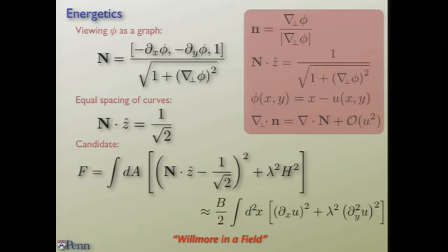The divergence of the layer normal, the normal to that green surface, is to the same order, to quadratic order, the same as the divergence of the nematic director in the smectic. Everyone get it? This lives in 2 dimensions. This lives in 3 dimensions. Its 3-dimensional divergence squared to the same order is the same as its 2-dimensional divergence squared. That's good.